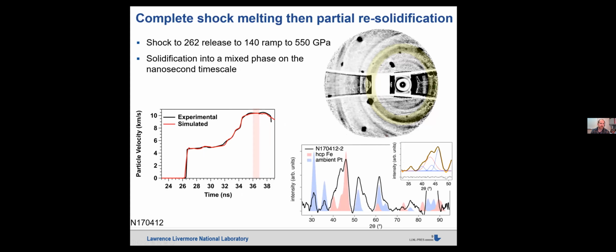Okay, so then if you increase that entropy, you increase that shock strength on the first shock, now shocking to 260 GPa, which is just into a completely molten state, releasing to 140 GPa, and then ramping back up to 550 GPa, we observe partial solidification. So solidification, we observe with the diffraction pattern, a mixed phase state of both liquid and solid, which, in a qualitative sense, you see a bit of a halo around that same HCP triplet.